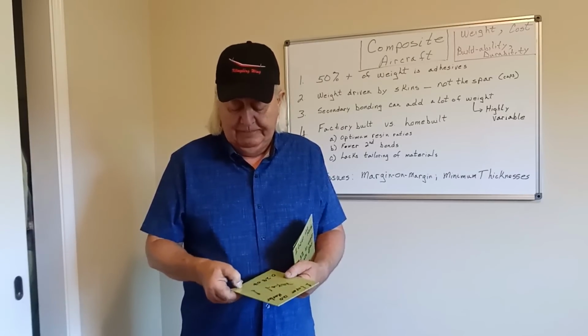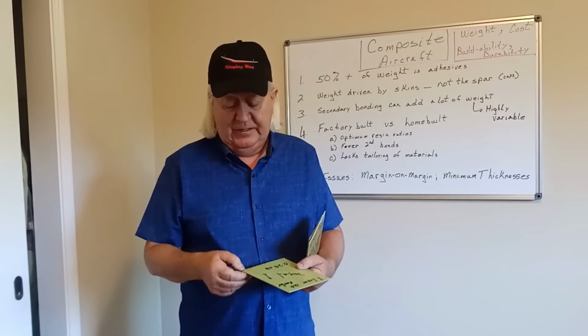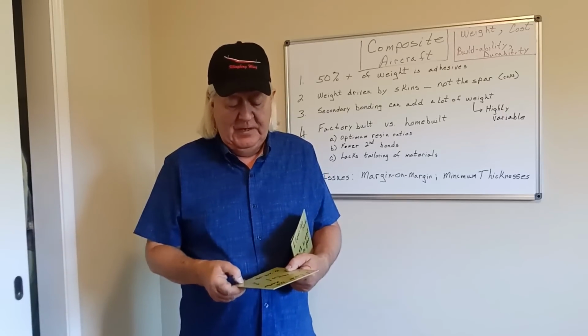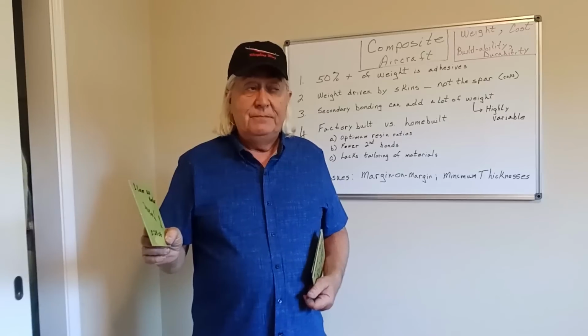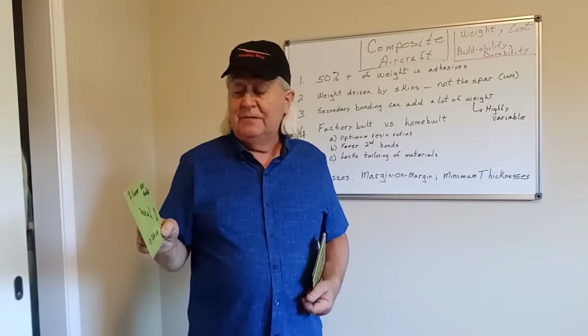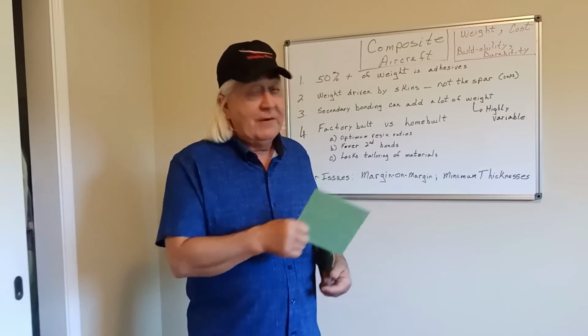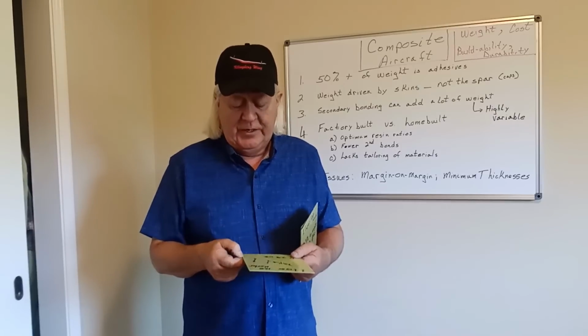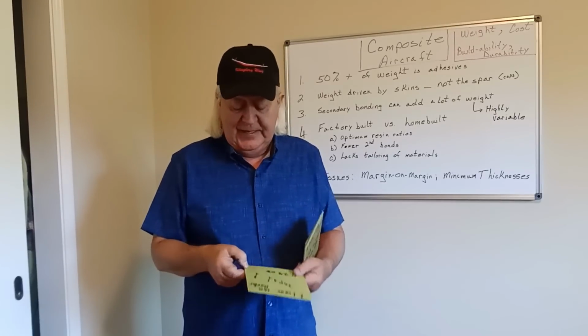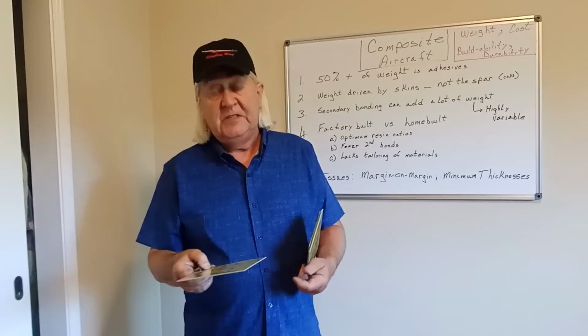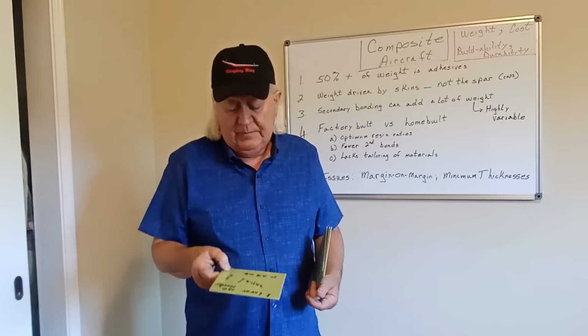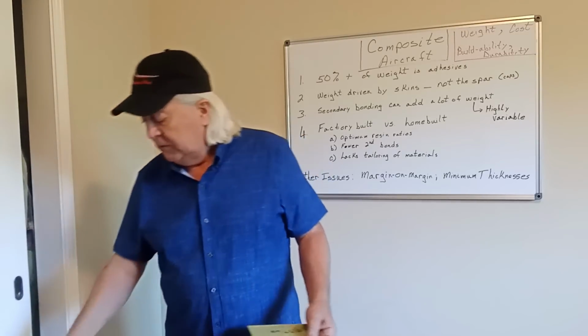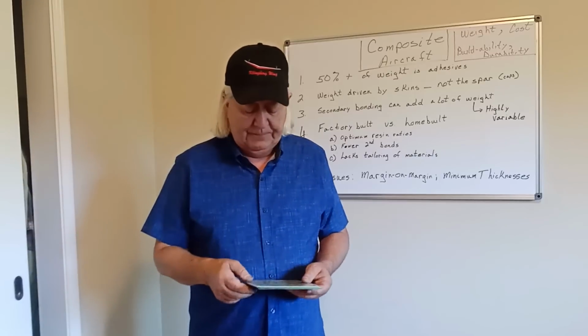1 layer Kevlar. In my world, I'd call it the same. But it's half the weight. This is half the weight of the fiberglass for 1 layer of this. 1 layer of the fiberglass I showed you, almost twice the weight. And the dent resistance, it's not worse here. It might actually be a little bit better. So 0.28 ounces for that.